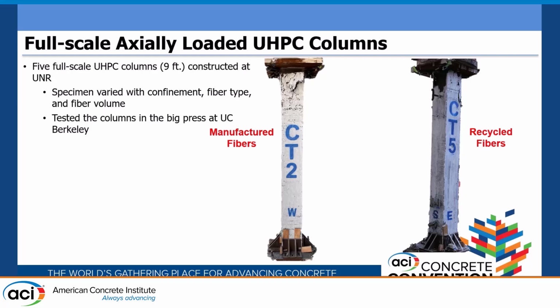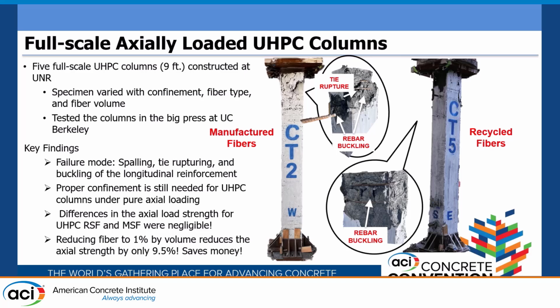I don't know if you know that machine that they have. It's a big one that can test high axial columns. The key findings that we saw are that pretty much all the failures are spalling, tie rupturing, and buckling of the longitudinal reinforcement. We saw that proper confinement is still needed for UHPC under pure axial loading, and also that the difference in axial strength between manufactured fibers and recycled fibers is pretty much none.